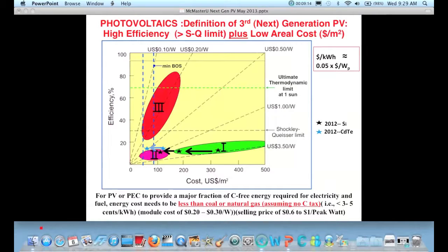And this is a plot of the efficiency, which is percent, but since you get 1 kilowatt per square meter with no clouds at high noon, you can just multiply this fractional efficiency by 1,000 to get watts per square meter. So if you divide dollars per square meter by watts per square meter, that gives you the inverse slope of this line, and you get a number which is how the panels, say for PV, are rated. They used to be about $3.50 per peak watt, because on average the cost was $350 a square meter, and 10% efficient, that would give you $3.50.